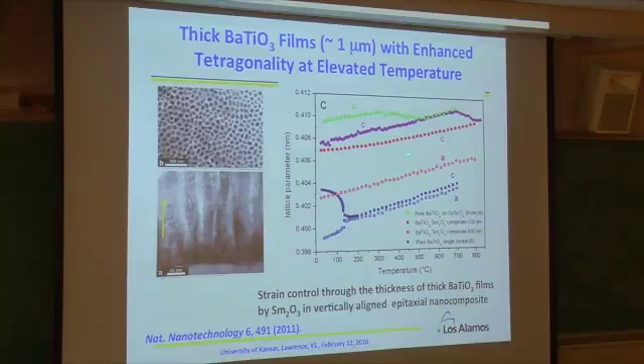If you look at the lattice parameter, look at the bulk. For example, this is barium titanate. Below this temperature, it's tetragonal. Above this Curie temperature, it's cubic. So C does not equal A. That's for the single crystal. But when you do the pillar structure here, for example, this top view, look at this. You have all these pillars inside, and then look at the vertical structure. And actually, even at 700 degrees C, you still have that kind of tetragonality. Of course, we cannot say whether it's ferroelectric at that temperature, but we checked up to 300 degrees C, and it's still ferroelectric. So you really change the functionality you can achieve with it.